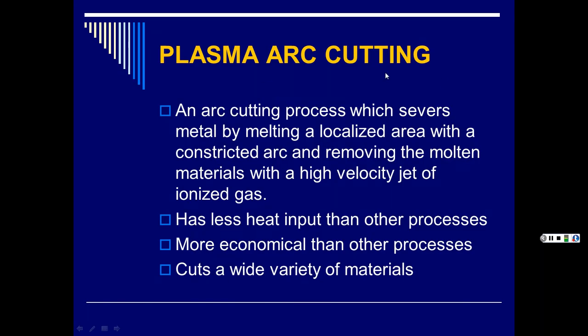Then we get into plasma arc cutting. Now here, we talked about oxyacetylene cutting with that extra attachment on there. And if you've ever done that, it takes a while to get it right. And then you're trying to cut it and you don't have it just right, and then the puddle's fusing back again. And you really kind of have to know and play with it. Now this plasma arc's pretty good. You set it up, and you go along and you see these sparks everywhere. But it cuts it, you know, half or an eighth, that much thinner than oxyacetylene cutting. And if you hold it right, you can get a nice, straight, perfect cut.